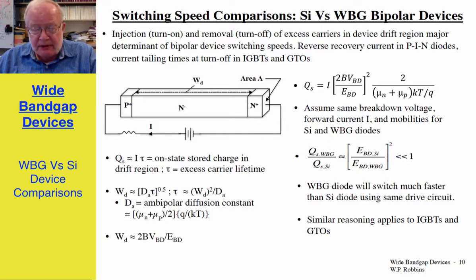Switching speed comparisons. If we do a bipolar comparison, I show here a PN junction, PIN diode, forward biased with some current I. The excess stored charge in the drift region is approximately I times the carrier lifetime. The drift region length has to be approximately or somewhat smaller than the diffusion length, which is the square root of the ambipolar diffusion constant times the carrier lifetime.